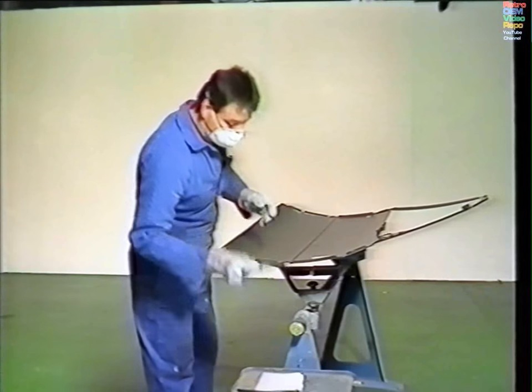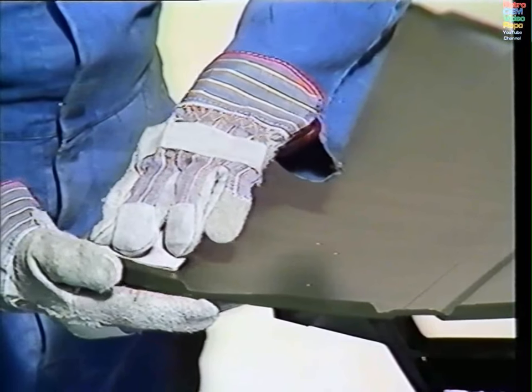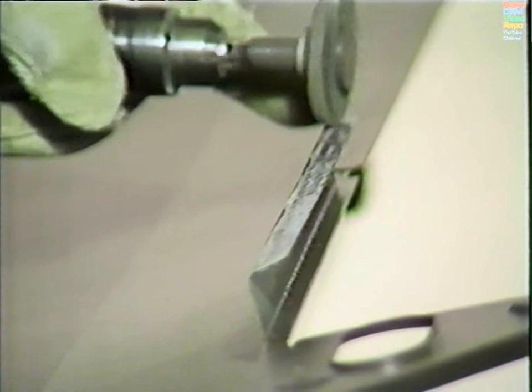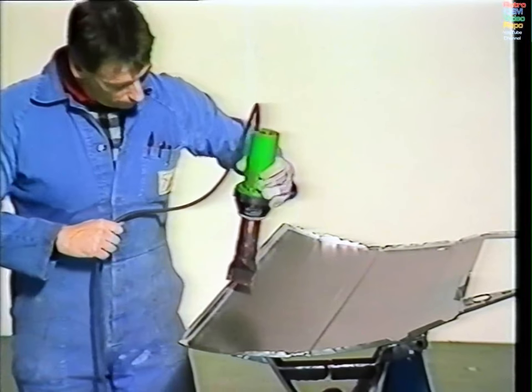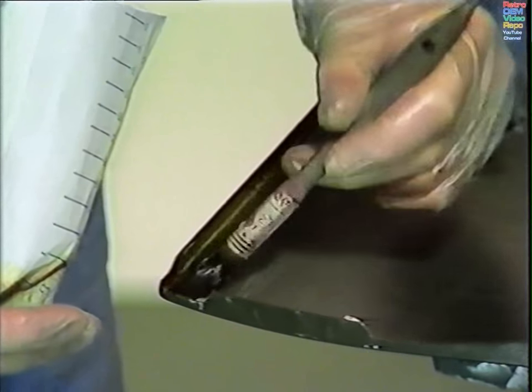The new skin is then prepared. Acomet primer is to be applied, and so the manufacturer's primer is removed. Areas to be spot welded, such as the quarter light reinforcement rail, are cleaned off with a wire brush and treated with weld-through primer. A hot air gun is used to remove moisture, and the Acomet primer is applied and dried off the same procedure as was carried out on the Rover 800.